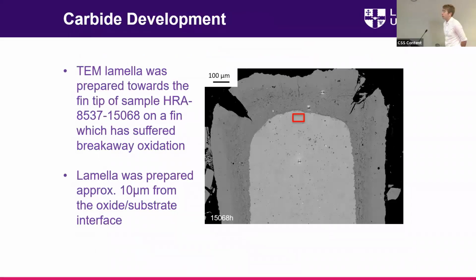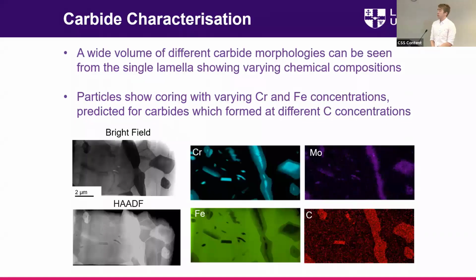So to further characterize these carbides and see what's happening, we prepared some TEM lamellae from the middle of a breakaway fin, a fin which had suffered breakaway. And this was prepared from near to the oxide substrate interface. So you can see there's quite a few different types of particles present in the material, with varying compositions. For example, on the right hand side there's cored particles, there's some particles with chromium rich down the middle, some with molybdenum, some without molybdenum.